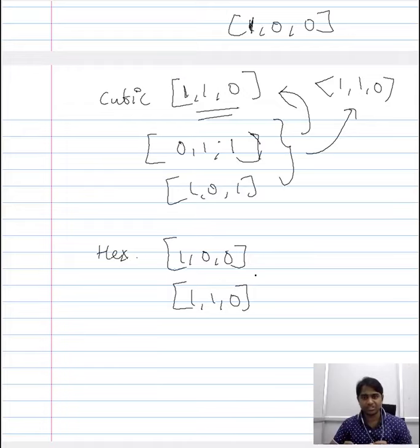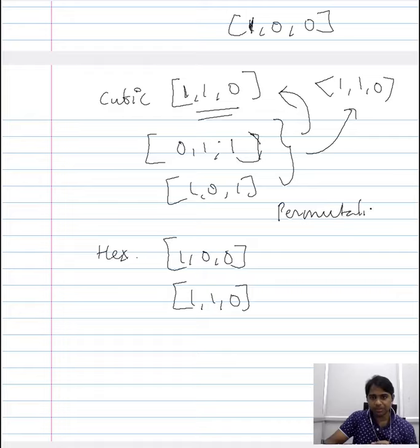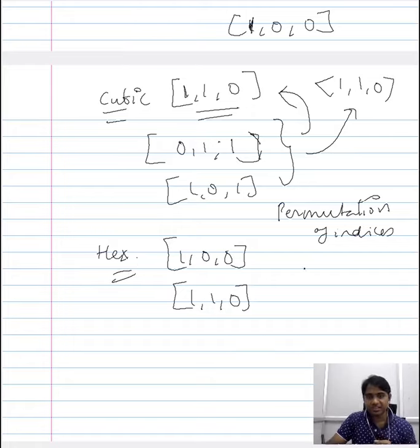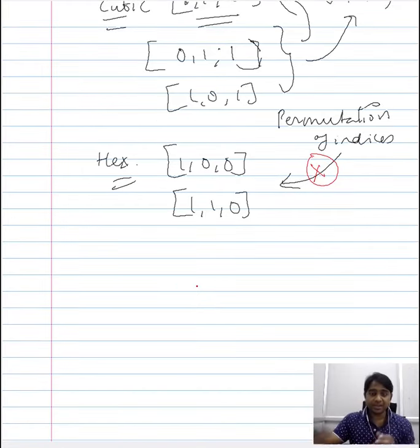So when you consider just the Miller indices, in hexagonal close packing the family moves beyond the permutation of integers, whereas in cubic it is confined to the permutation of integers. In hexagonal close packing this does not hold, and that is the reason why we introduce another index, another integer, and then your overall representation of the direction and the plane within the hexagonal close packing will require 4 integers.